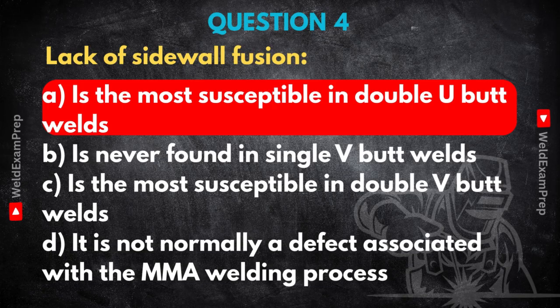Option C, most susceptible in double V butt welds. Generally not considered most susceptible compared to the U groove. While it can happen in a double V, that steeper, tighter U profile often presents the bigger challenge for fusion. And D, not normally associated with MMA. Completely false. Lack of sidewall fusion is a common potential defect in many processes, including MMA. If the welder doesn't maintain the right arc length, travel speed, or current, it can happen easily.